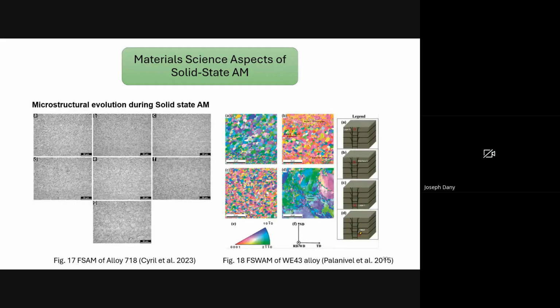The underlying layers experience varying degrees of thermal exposure depending on the spatial location relative to the heat source. So heat flows downward through the cooler substrate material and upward through newly deposited material, which leads to different cooling rates and temperature profiles layer to layer. And the second one is the reheating effect. Higher layers are subjected to partial reheating by subsequent deposition passes. This reheating can increase the local temperature of lower layers just enough to cause some grain growth or additional dynamic recrystallization, which alters the microstructure compared to the freshly deposited top layer. The extent of reheating is influenced by process parameters and interlayer time delays.